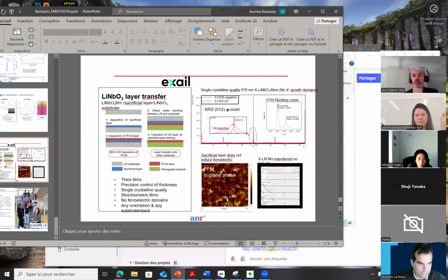So in terms of film quality, is there any advantage in the homoepitaxial growth compared to the epitaxial on sapphire or silicon? Of course. If you look, for example, this film is already very thick, 680 nanometers, and you don't have any growth domains. It has a very low rocking curve. The same film on sapphire, you see, these phi scans are much broader. And the film on sapphire with this thickness is already cracked. You have domains, you have twins, and you have cracks, because it relaxed the stresses. Like this film, we don't have all these problems. Okay. Thank you very much.